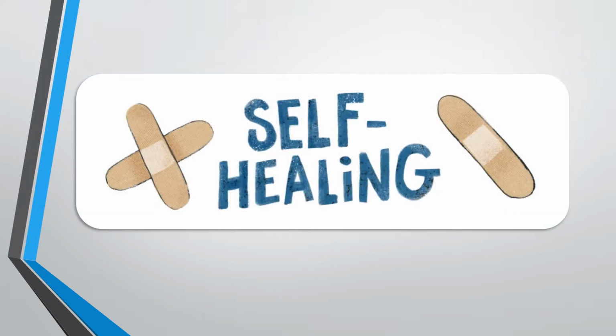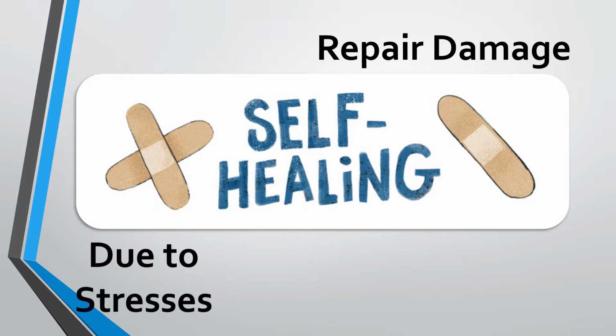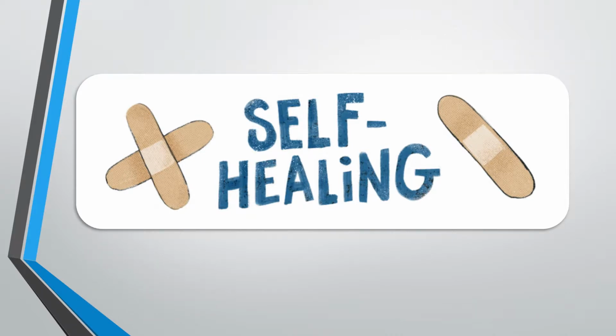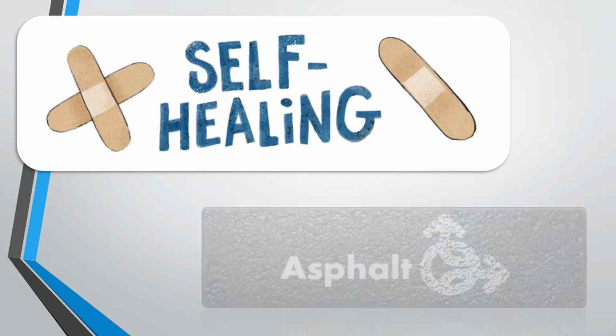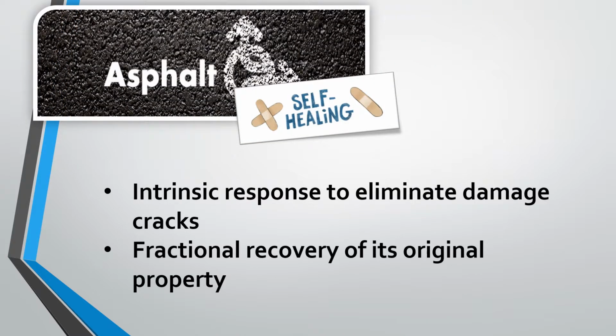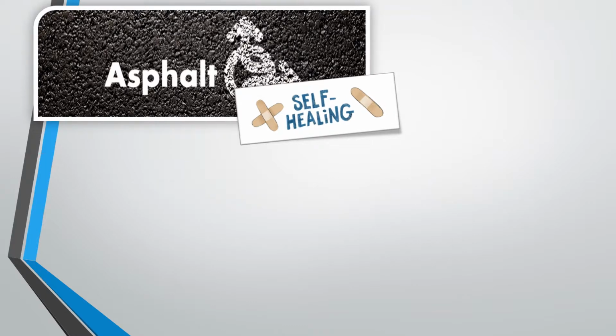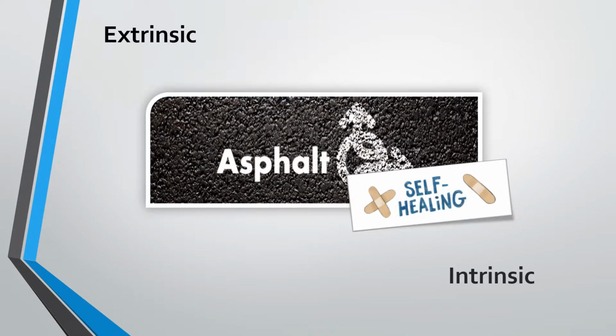Self-healing is a process by which a material tends to repair the damage induced by different types of stresses. According to many studies, self-healing is the asphalt's intrinsic response to eliminate damaged cracks and subsequently bring fractional recovery of its original properties. Basically, there are two types of self-healing, namely extrinsic and intrinsic. Extrinsic self-healing materials heal through encapsulation of a healing agent like a microcapsule within a material matrix, which is released after cracking. On the other hand, intrinsic self-healing is a material's ability to recover its properties in the presence of reversible chemical bonds.